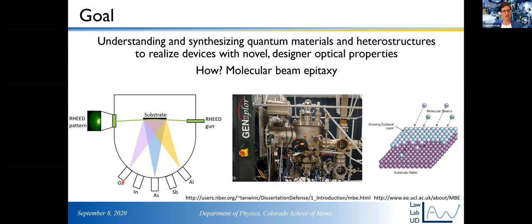And what we do is we have different elemental sources. So our gallium source is literally just chunks of gallium sitting inside a crucible that we heat up. The gallium evaporates, it hits the substrate, and the atoms, if you look in the schematic on the right, the atoms hit the substrate and they can diffuse around on the substrate to find a low free energy position, a good position.